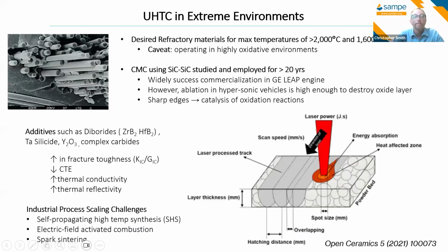So next slide. On the other side, we have the inorganics. So ultra high temperature ceramics have been used for temperatures greater than 1,000 C. So there is a big desire to have refractory materials that can withstand 2,000, even 3,000 degrees C. And the caveat for a lot of these, especially for use in hypersonics, is they're operating in an extremely oxidative ablative environment. And so this can be detrimental to the part shape and the protective oxide layer.